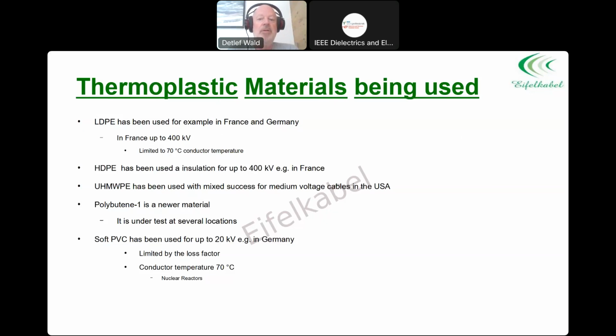So looking at thermoplastic materials, they are not that new. We have LDPE that has been used, for example, in France and Germany, in France even up to 400 kV. Their limitation was that it had 70 degrees conductor temperature and 150, 160 degrees short circuit temperature, so you were limited in conductor size. The HDPE also has been used, for example, in France for up to 400 kV. And both of them, these cables are, according to my information, still in service.